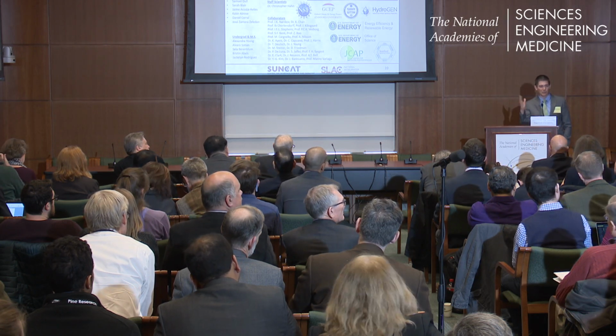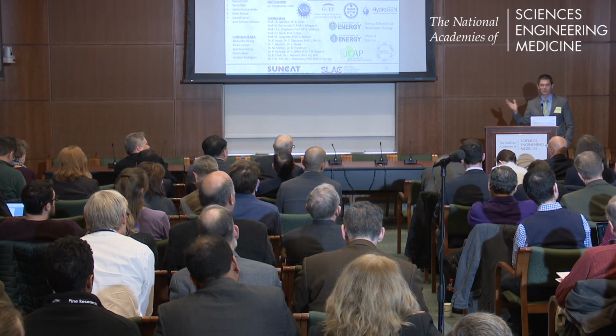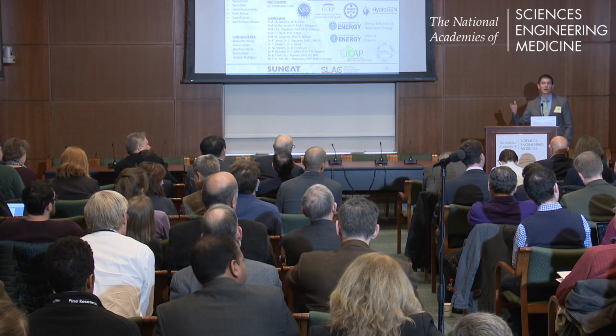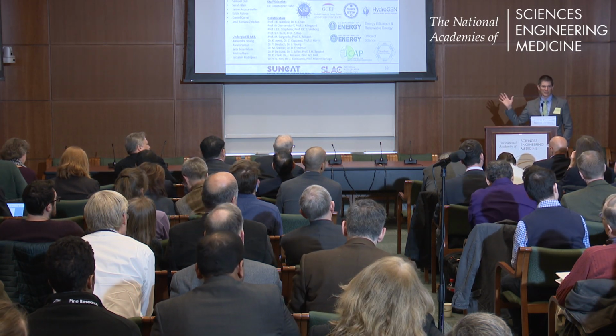Absolutely. Oxygen remains one of the greatest challenges. And as Mark mentioned, there's an over-potential there for these multi-electron processes. And in this case, even Mother Nature hasn't come up with it. So as marvelous as Photosystem 2 is, even that requires an over-potential to go. And so I think there's a lot to be understood about water oxidation, and for that matter, oxygen reduction as well, as a function not just of the material, but the electrolyte. Is it an acid? Is it base? Is it neutral? We have to think of any of these technologies. There's going to be a native condition depending on the product you're looking to make, and we need a good, probably water oxidation catalyst to couple to that.